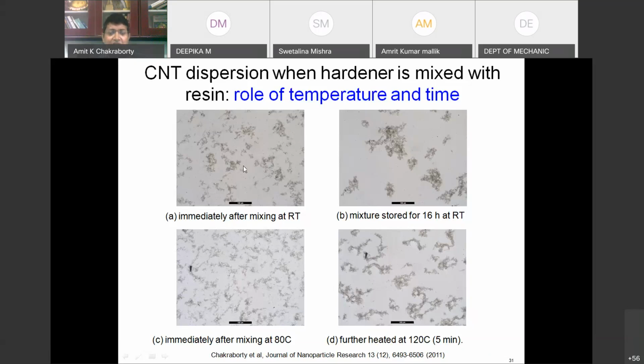So what is this? Basically, as soon as you add the hardener, there are two parts. Initially, you mix the resin, mix the nanoparticles in the resin. Then, after you have achieved very good dispersion, you have to add the hardener. The hardener is a different chemical altogether. So, once you add the hardener, the system changes again. The equilibrium of the dispersion of the particles changes. So, this is what we have seen: even immediately after mixing, as soon as you add the hardener, even at room temperature, the dispersion is changed.